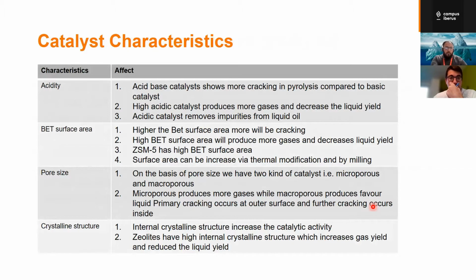Basically, there are various properties of the catalyst that impart different sorts of characteristics to the process itself: acidity, surface area, pore size, and the structure of the catalyst. An acid catalyst basically shows more cracking in pyrolysis compared to a basic catalyst, but at the same time, a highly acidic catalyst can produce more gases and decrease the liquid yield, which is not so good. The acid catalyst can also remove impurities from the oil.